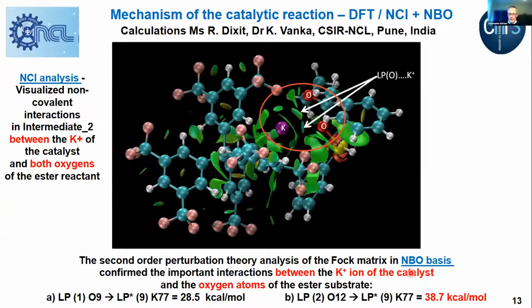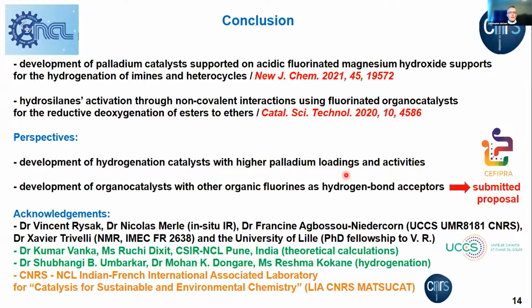So let me just already conclude and underline that we have developed, within the past years, interesting palladium catalysts supported on acidic fluorinated magnesium hydroxides for the hydrogenation of imines and heterocycles. In a second project, we have developed organocatalysts for hydrosilane activation through non-covalent interactions, and applied them for the reductive deoxygenation of esters to ethers. So both projects led to recent publications.